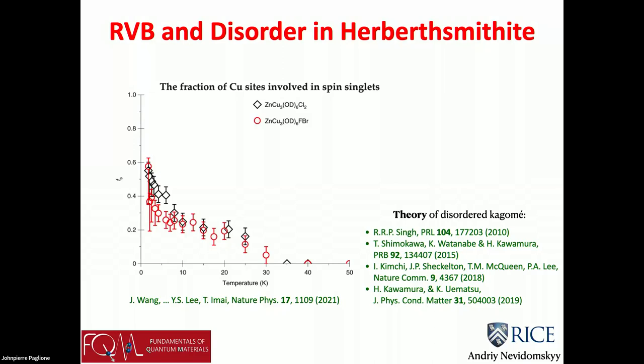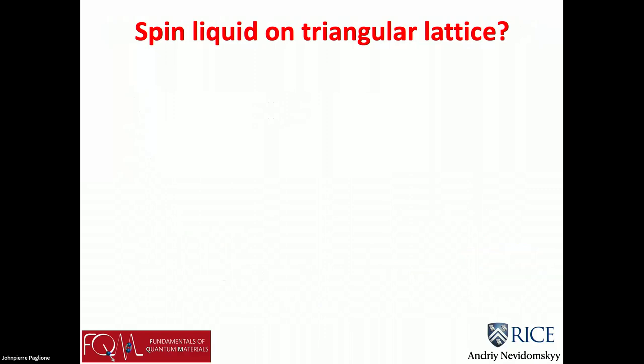bonds that form singlets? See, in a kagome lattice, ideally you want all of them to fluctuate from RVB. Unfortunately, the answer is only 60% of them do. What did the other 40% do? Well, they get ordered. And that's why people no longer believe, and there's a bunch of theory and experiment papers that I cite here, that barlowite and the Herbertsmithite, these two materials, that neither of them, unfortunately, are good examples.